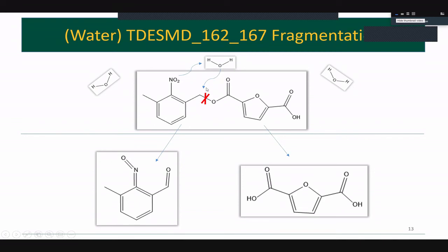These blue arrows are just to give you a flow of the mechanism, or what had happened. The bond between the carboxyl oxygen and the benzylic carbon had broken, so it had an open vacancy where the oxygen of the excited water was able to interact with this, and they were able to bond and form this unit below.